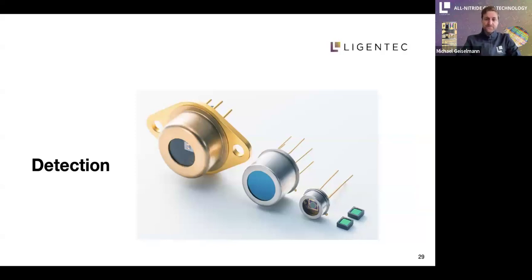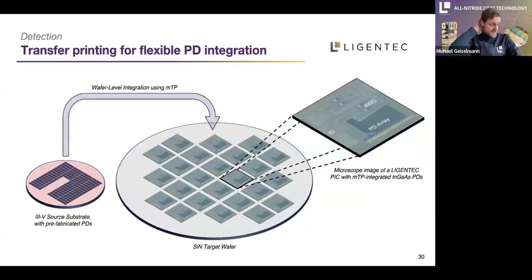In terms of detection, as already mentioned, we're doing transfer printing for flexible photodetector integration. And for those who are not familiar with this technique, you have a source wafer with fabricated photodetectors, and you take these photodetectors with a stamp and put them on a silicon nitride target wafer. That in the end you have your silicon nitride circuit, and your photodetectors put there with a microtransfer printing technique where needed.